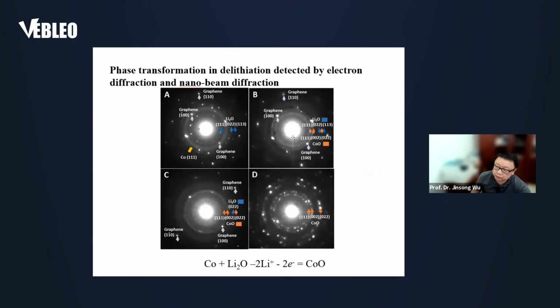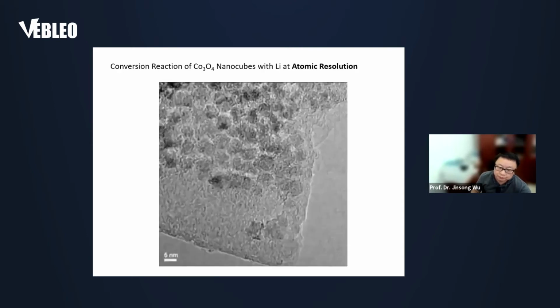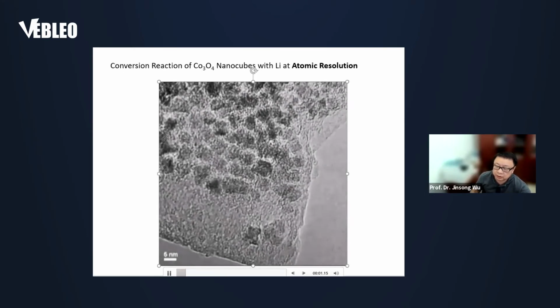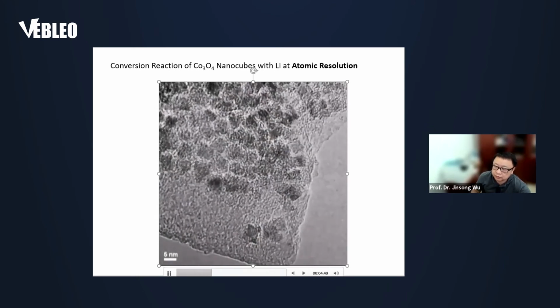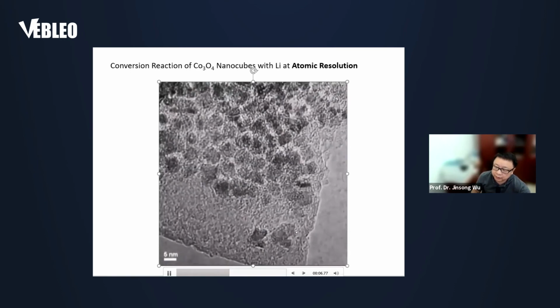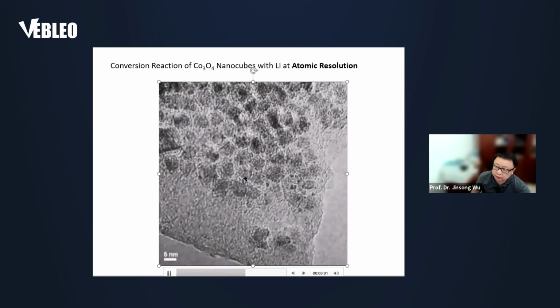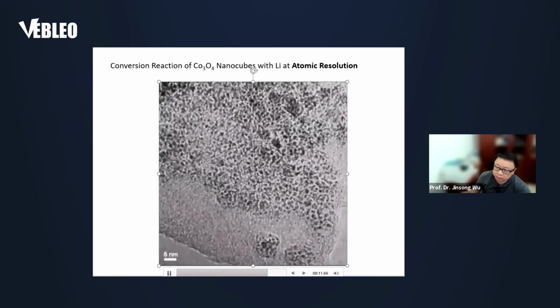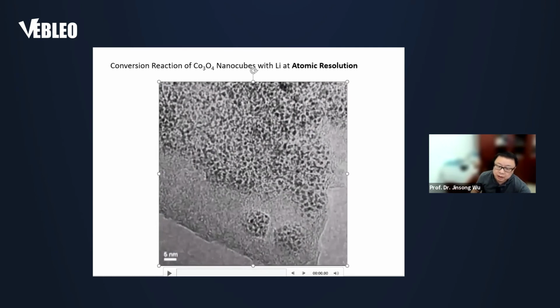Similarly, when we do the delithiation and look at the evolution of the electron diffraction, it is identified that the final product of the deconversion reaction is cobalt oxide, as shown here. So here the lithium oxide, as outlined by blue arrows, gradually disappears, and eventually what we have is cobalt oxide. And if we look at these reactions at a little bit higher magnification, you can see the expansion of the few-layer graphene as a substrate. And also you can see the cobalt oxide cubes become smaller particles.